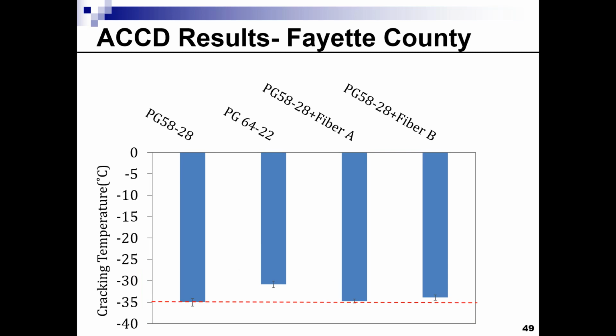If we go to Fayette County, and again, just to remind you that the mix being used in Fayette County is a 404 LVT or low volume traffic mix. So it's different than the other two mixes, because the other two mixes used were a type one mix. For Fayette County, what we're seeing is really no change in terms of the cracking temperature. It seems that the cracking temperature depends more on the base asphalt binder.